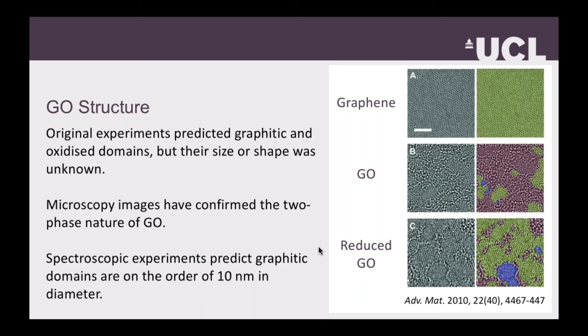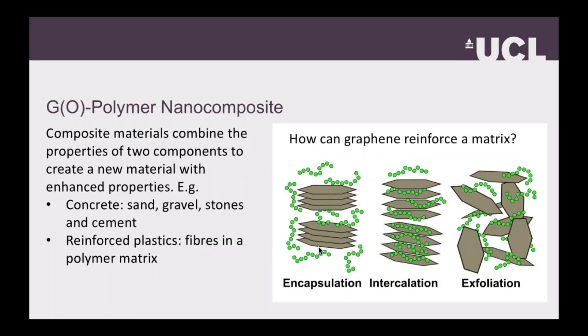The question is really how do we generate these structures accurately? These properties are interesting for many applications — we're interested primarily in material applications. When you have a polymer matrix, you want to disperse a particle within it. 2D particles, if fully exfoliated and exposed to the polymer matrix, can make the full matrix a lot stronger. Graphene oxide tends to be better than graphene in this case because the polymer-graphene oxide interaction is stronger and it is more likely to exfoliate.